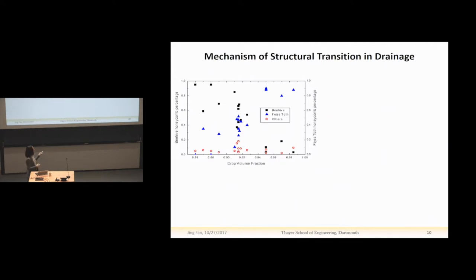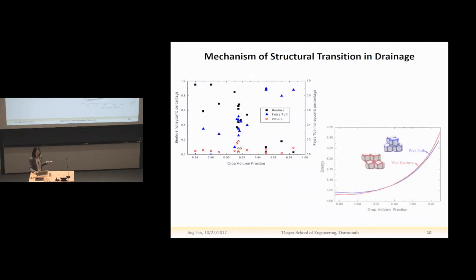And we found that when the drop volume fraction is below about 0.915, the beehive honeycomb is dominant. And when the drop volume fraction is higher than this value, the other FT honeycomb structure is dominant. And then we did the calculation. We calculate the interfacial energy, because interfacial area is proportional to interfacial energy. We calculate the non-dimensional interfacial area of those two structures over a wide range of drop volume fraction.